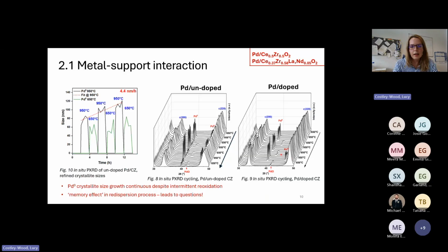We can track the crystallite size of the palladium metal, from these sharp reflections here, over the cycles. Another interesting effect we observe is that even after we reoxidize the majority or all of our palladium back to palladium oxide, which is dispersed over the surface, when we heat it up again and cycle again, the palladium continues to grow, as you see here, from the temperature it achieved during the previous cycle. So we have this memory effect going on.